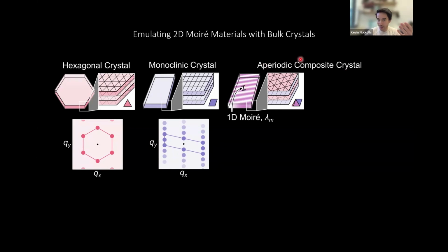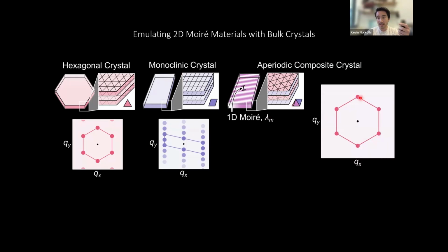So this target reaction product we would call an aperiodic composite crystal. It's a crystal because it's a rock that I pull out of a high temperature furnace. It's aperiodic because it doesn't have translation symmetry. And we would call it a composite crystal because it's made up of these two different sublattices. It's effectively half hexagonal, half monoclinic. So this crystal, just like these simpler crystals, can also be identified by its symmetries and diffraction. We should expect to see the hexagonal Bragg peaks superimposed upon the monoclinic Bragg peaks.